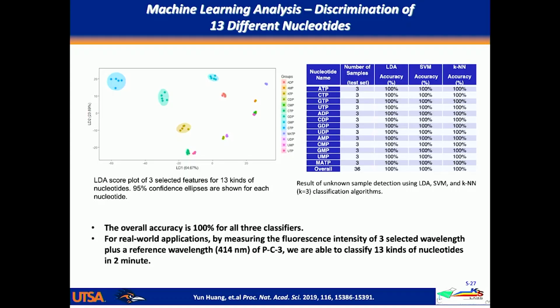And I had a student who was quite interested in AI, and this actually goes back to before the AI boom. This work was done around 2017 to 2018, and we published it in 2019. But what my student Yun Huang did was he took that polyelectrolyte and he looked at the quenching of it with a variety of different phosphate derivatives, ATP, GMP, et cetera, and then also using some oligonucleotides. And then he trained the spectra with different machine learning models. And he was able to discriminate based on the spectral shape which ion the polyelectrolyte was interacting with. So he could identify the nature of the phosphate in the solution just based on a training model.